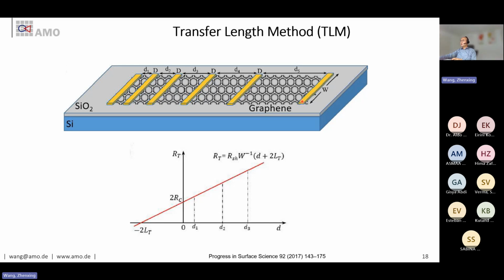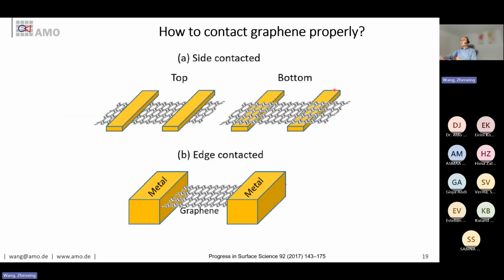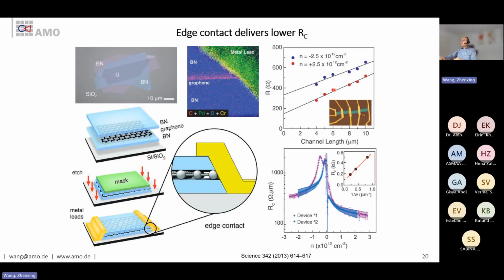Of course, normally this also has to be normalized by the width of the channel, because this also plays a role. The wider the channel, the smaller the contact resistance. But usually when you normalize it, then you can compare it. So there are also different geometries to contact graphene, like you can contact from the top, from the bottom, or from the edge even. So of course we know edge contact delivers a lower contact resistance, as this is an example from more than 10 years ago, where they encapsulate graphene into 2 boron nitride layers, and then they contact graphene from the edge. Then they can really achieve below 200 ohm micrometer contact resistance.